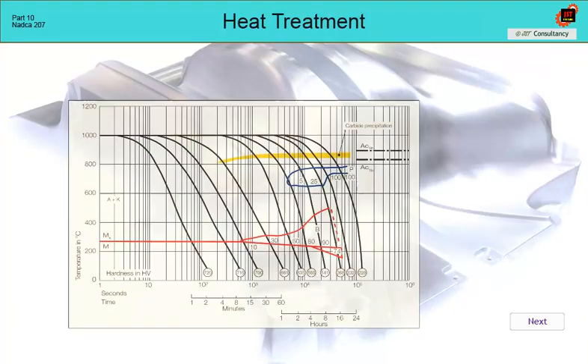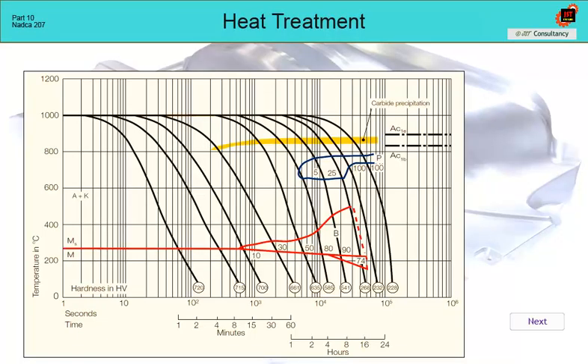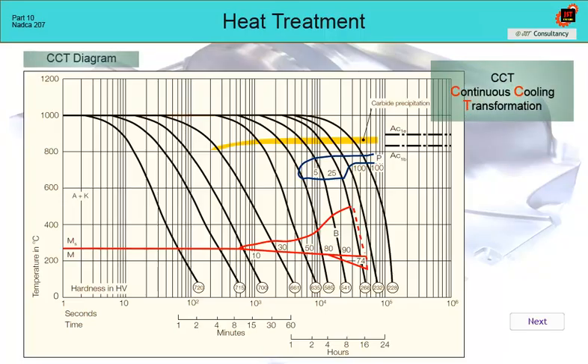How the phase transformation in steel occurs is usually shown on the so-called CCT diagram. CCT is an abbreviation for continuous cooling transformation. At different cooling rates, the transformation curves of martensite, bainite, pearlite, carbides, and other phases in steel are analyzed. The user, especially the technologist, is able to determine from the diagram both the necessary temperatures for austenitization and the necessary cooling rate of the steel to achieve the desired structure. This diagram is therefore a basic document for technologists to determine the parameters of heat treatment.